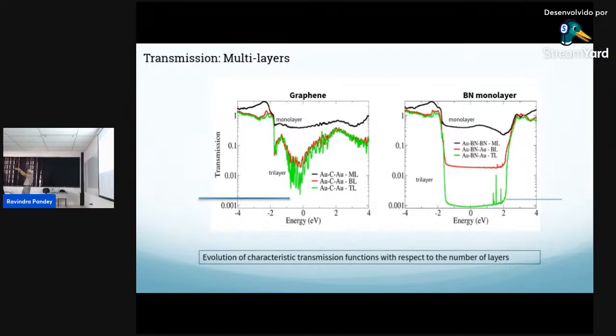What happens if we increase the thickness of the material? Monolayer, bilayer, trilayer. So it's going to reduce the interface effect. You can see here graphene is a monolayer. This is the bilayer and trilayer. You have the Fermi level. Transmission goes down but remains finite. The boron nitride case, monolayer, bilayer, and trilayer, just behaves like a semiconductor. I don't know if you remember this curve.